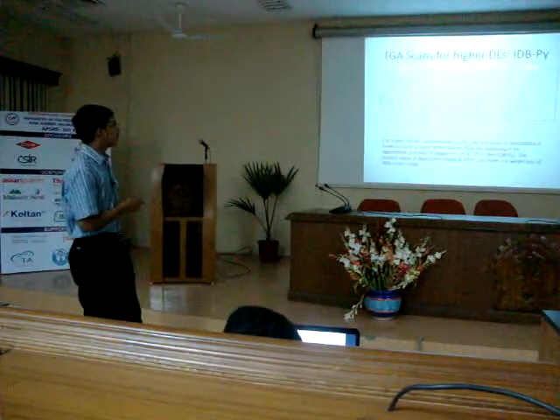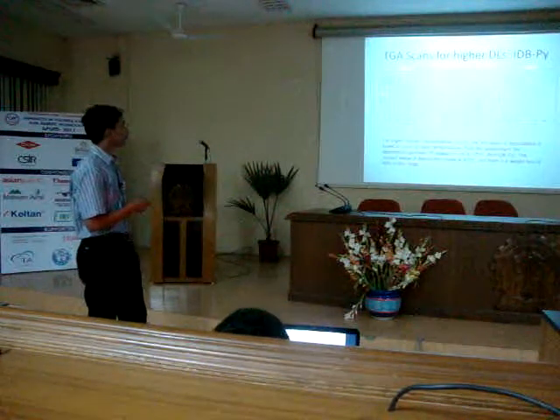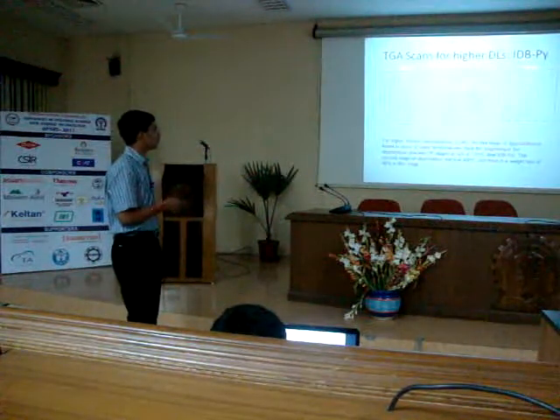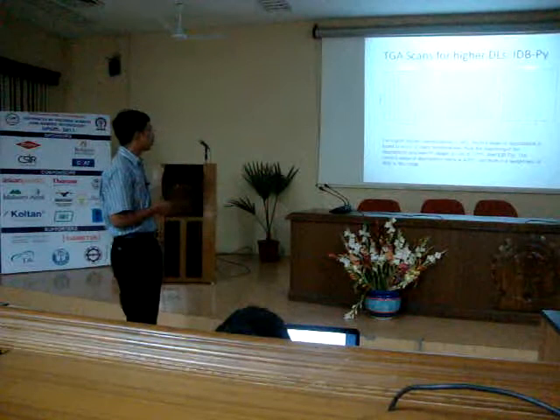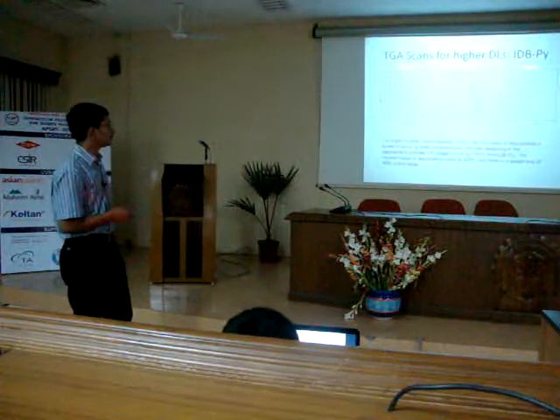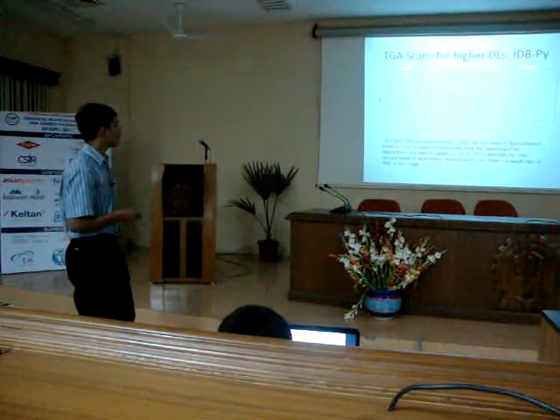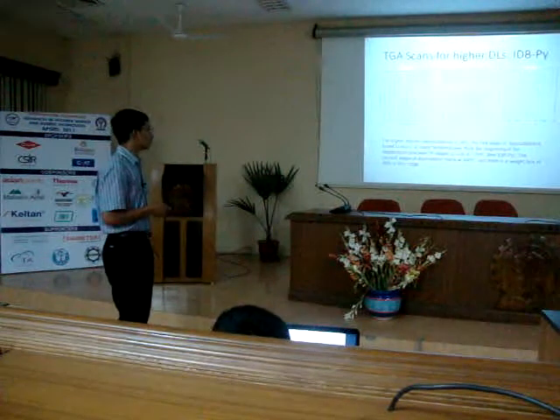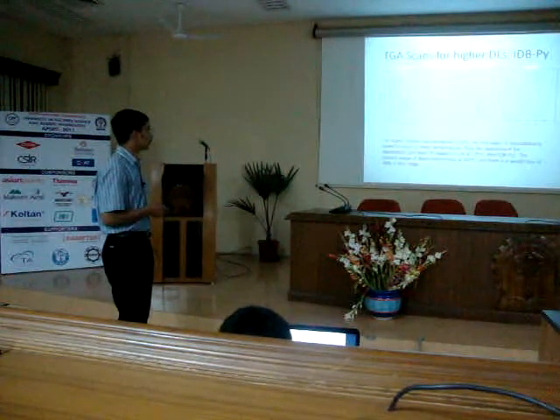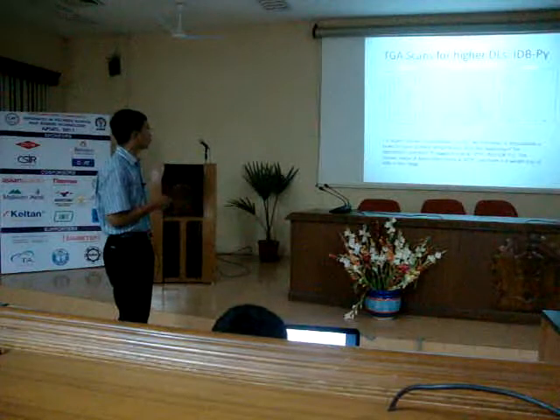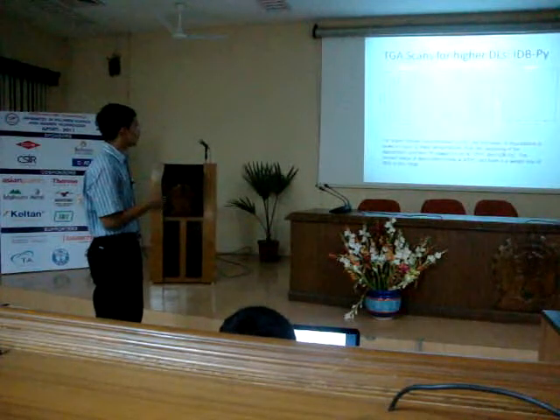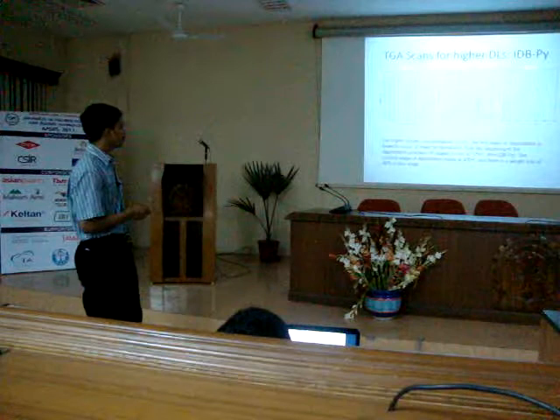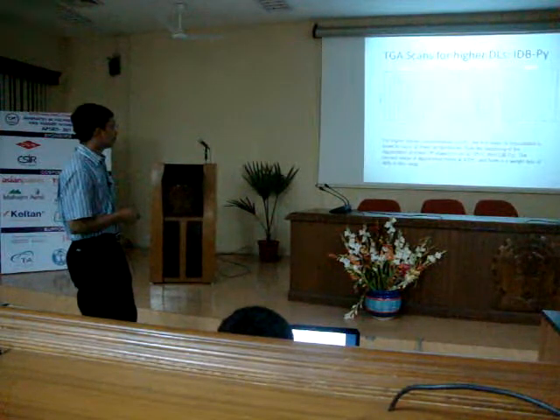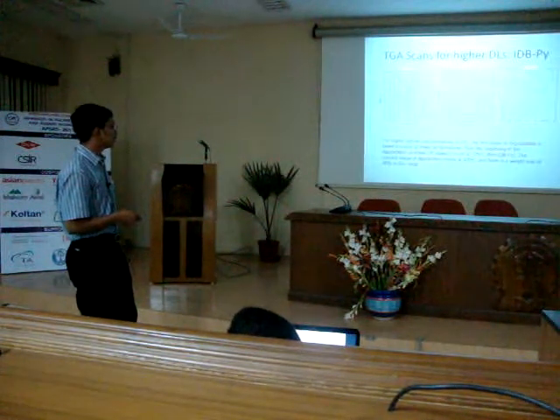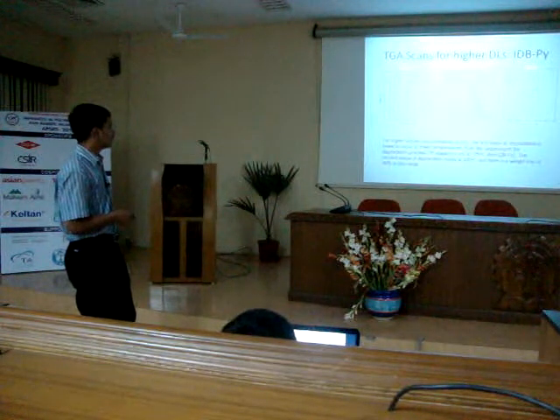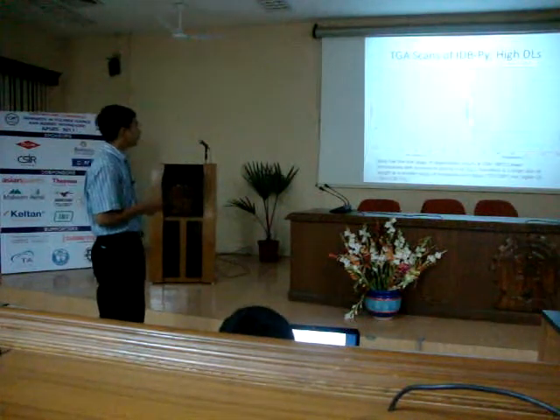So these are the TGA scans for higher doping levels. This is for 6 mol% IDB-Py, this is for 7 mol%, and this is for 8 mol%. For higher dopant concentrations, the first stage of degradation is found to occur at lower temperatures. Note the beginning of the degradation process occurs at 175 degrees Celsius for this one, for 6 mol% IDB-Py to PPY. Then the second stage of the degradation starts at 400 degrees Celsius and there is a weight loss of 40% in this stage. Next slide.